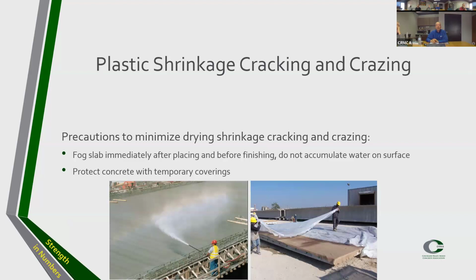Precautions to minimize plastic shrinkage, cracking, and crazing. Fog the slab immediately after placing and before finishing. Just make sure that there's no water accumulation on the surface, or protect the concrete with temporary coverings, plastic sheeting, wet burlap. The thing with plastic sheeting might be that you're going to see some streaks, but what we see generally here, especially in Colorado Springs, they do a lot of the gutters and the curbs right now, and they're mostly protected with plastic sheeting.